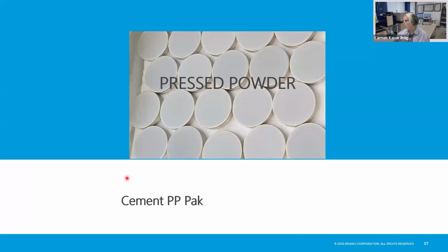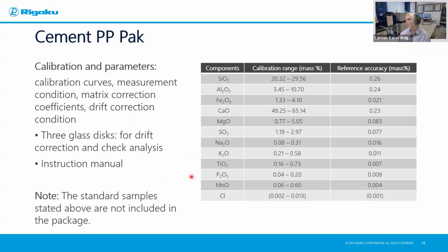Okay, so if we look at the pressed powder method, we also offer at Rigaku what we call the cement pressed powder calibration method. It's also a pre-calibration method. And of course, this is the example of the analytical range and the accuracy that can be achieved from silica all the way up to the element chlorine. But please note, because of matrix matching, it would be ideal for you to add additional standards onto this calibration to extend it to have the matrix matching. Yeah. So at least 95% of your results should represent the matrix that you have, because of course pressed powder has the drawback in that we need to have matrix matching standards.